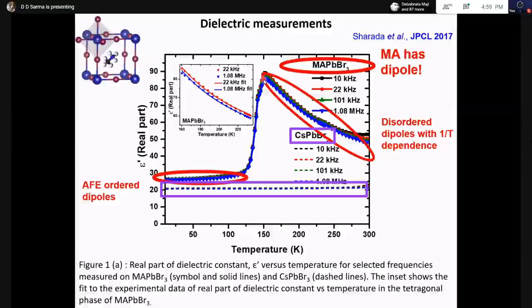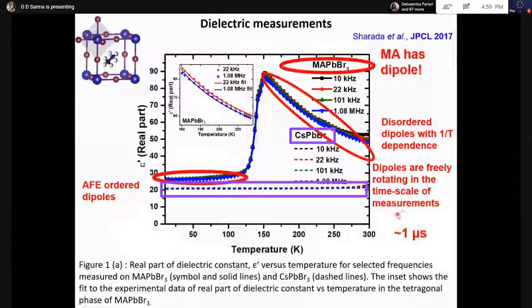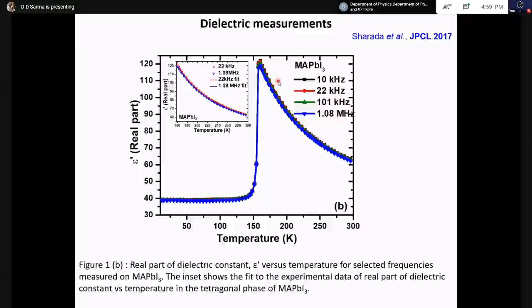If I look at it with a millisecond, then it will not look rotating. So it really depends on the probe. The fastest probe we use is about 1 megahertz, which is like 1 microsecond. That means down to about 1 microsecond, it looks like freely rotating. So it is rotating at a rotational speed much faster than 1 microsecond. The same story for MAPbI3, you can see 1 over T dependency. There's the antiferroelectric state looking like CsPbI3, and there's MA rotating, again, much faster than 1 microsecond.